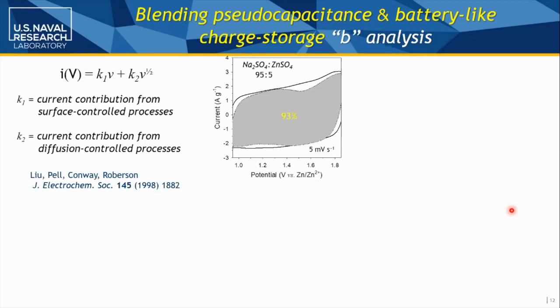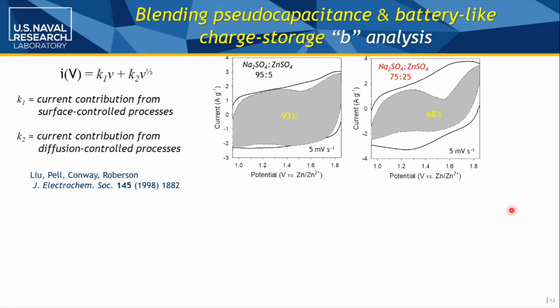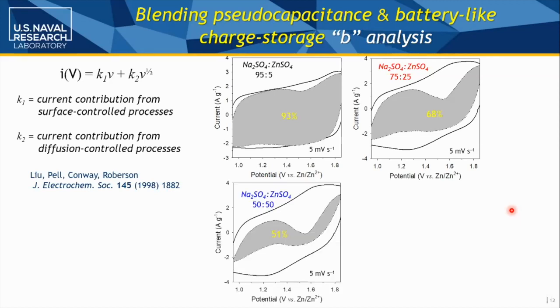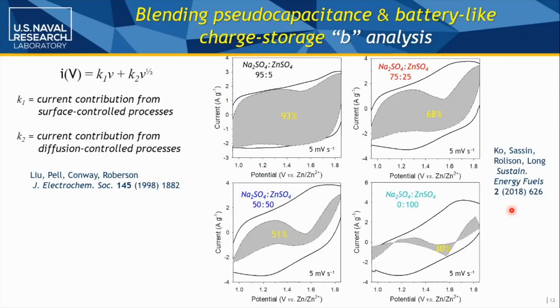So this is very sodium rich, so it should be mostly pseudocapacitive. So, okay, here's less sodium, more zinc, starts to look a little bit like a dinosaur. Here's 50-50 and here's all battery. So yes, your response should be to shudder. We are vehemently opposed to this analysis of charge storing materials in either a half cell or a full cell, because as your eye can tell you, it's this side of ludicrous.